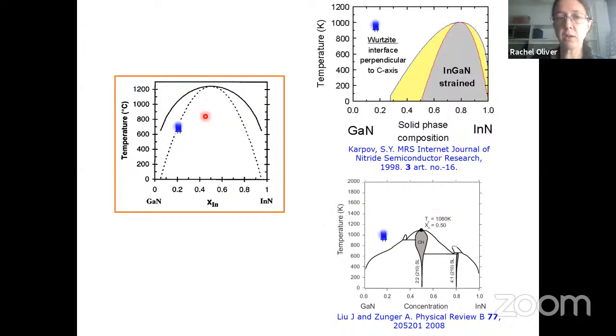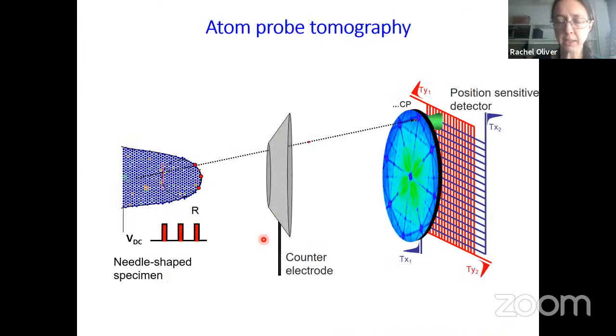So a lot of the understanding of the early TEM data was based on the Ho and Stringfellow predictions, but it doesn't take into account the fact that strain should suppress that decomposition into indium-rich and gallium-rich regions. Okay. So a metallurgist would go and look at the phase diagram. Great, well done, metallurgist. But really now we've got 3 different phase diagrams and we still don't know what's going on.